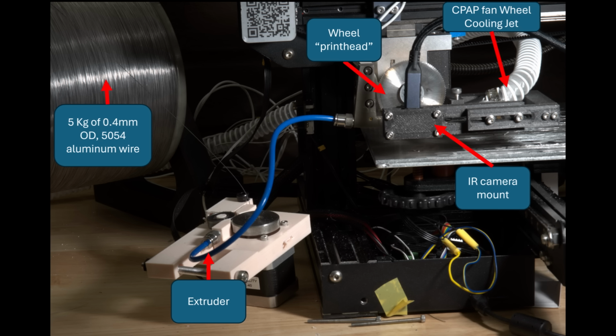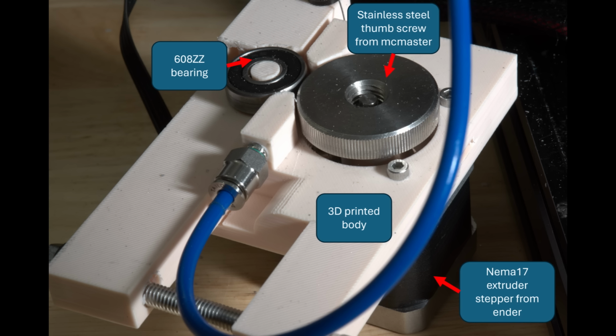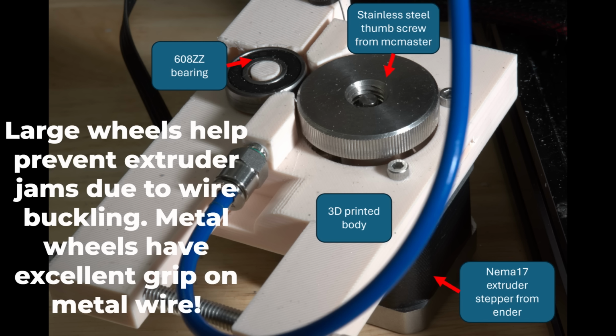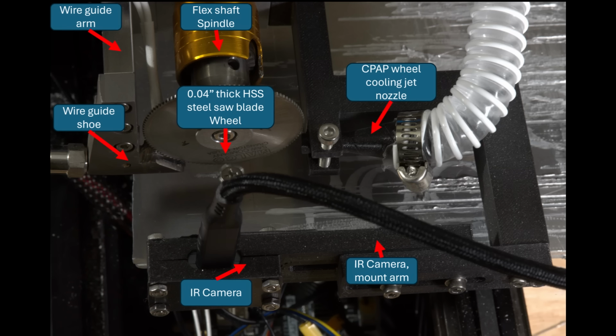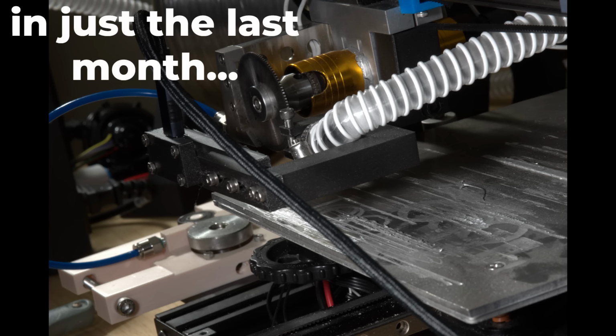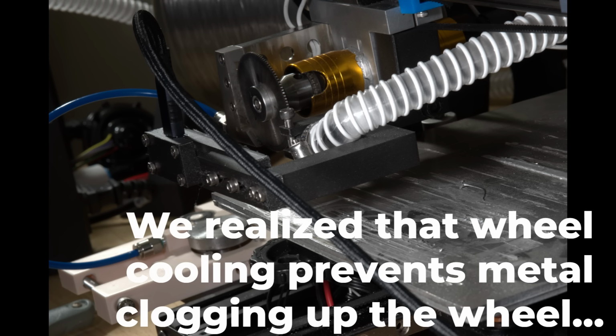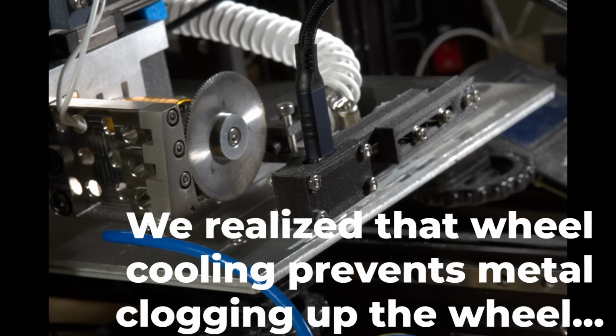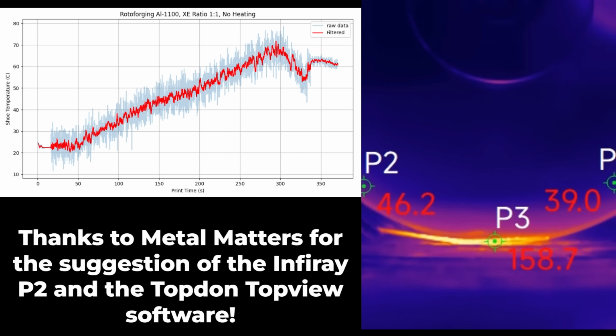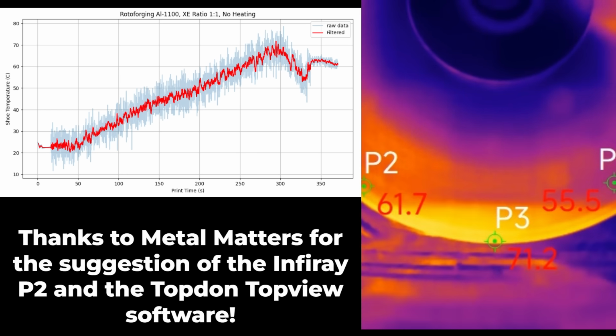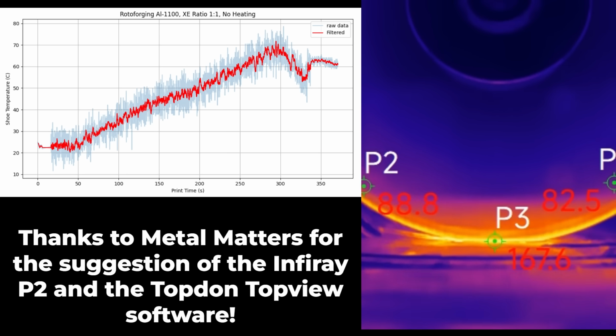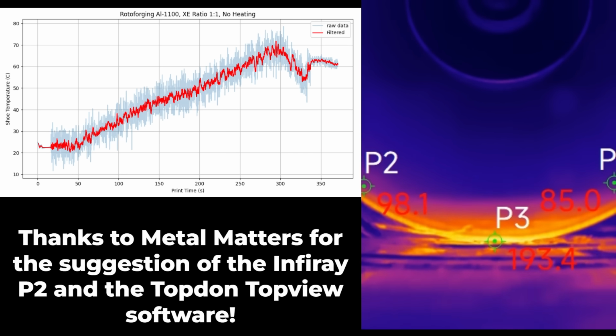Of course, then we started to wonder, well, can we make this system any better? And we added a better extruder, 5000 series wire, more contact area for the wire going through the extruder, a thermal camera, a wheel cooling duct using a CPAP fan, preheating to the wire guide shoe, and a variety of other control and quality of life features that we hope to be able to use to further reduce the deposition forces and give us access to stronger materials. And here's an example of a thermal camera run of printing 5000 series or 1100 series aluminum from our new thermal camera mount, courtesy of Sam.